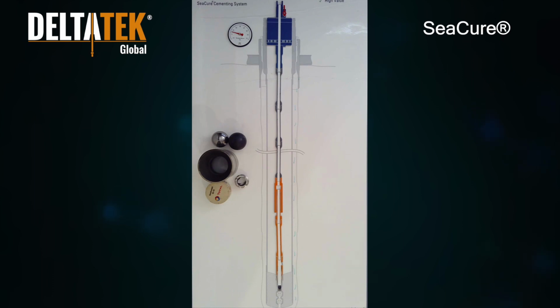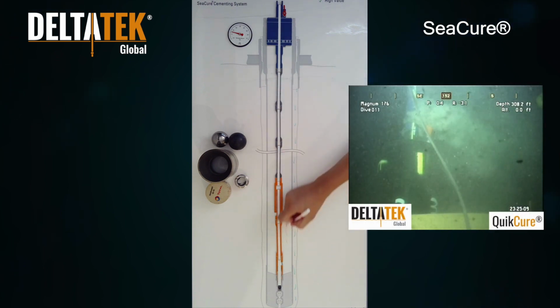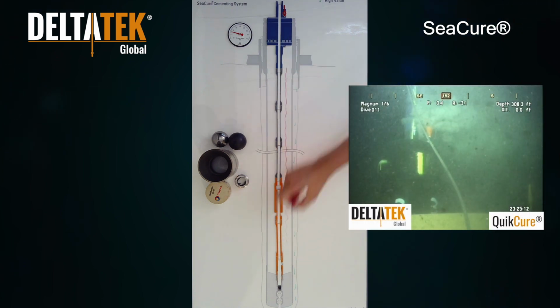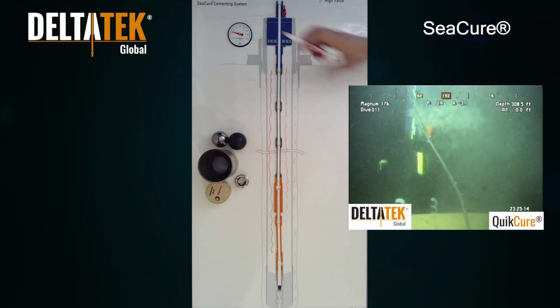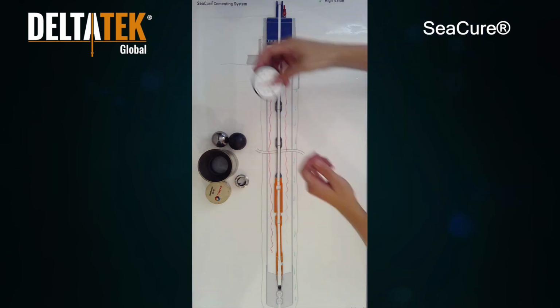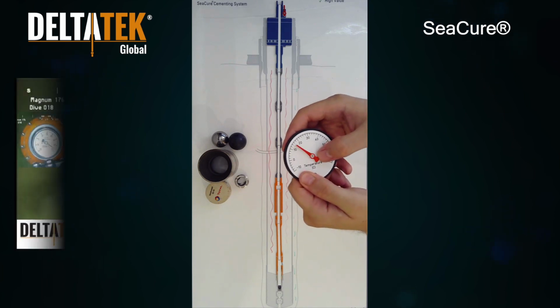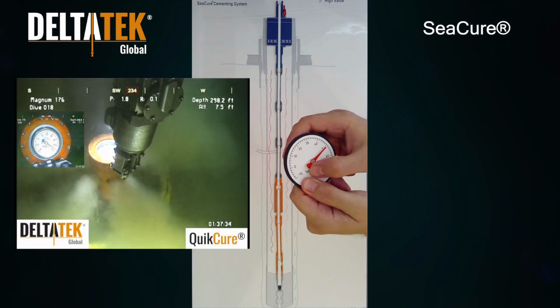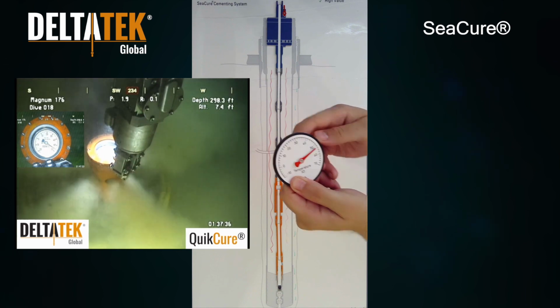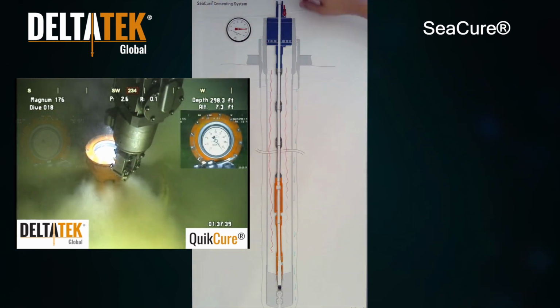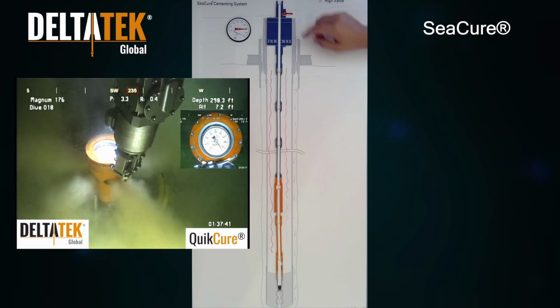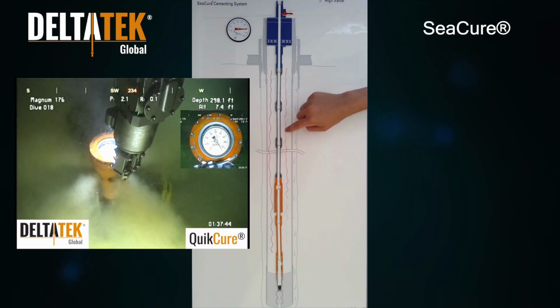The quick cure process utilizes a pit of seawater that's been preheated on the rig to approximately 65 degrees Celsius or 150 Fahrenheit. This heat sweep is then rapidly circulated into the inner annulus. After the casing bore has been filled with the heat sweep, a maximal exit temperature is observed on an analog temperature gauge that's been pre-installed on the running tool's ball valve. At this point, the ball valve can be closed to allow the additional heat to soak through the casing wall and into the slurry.